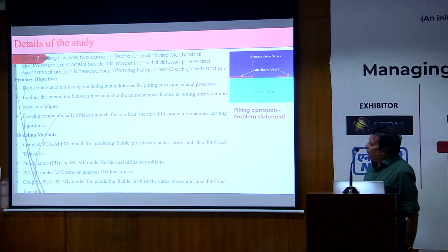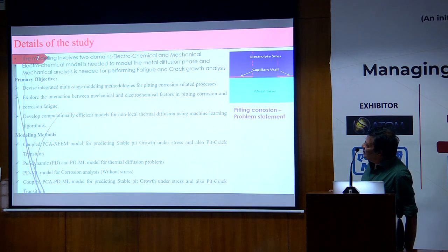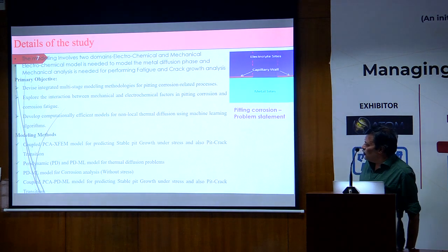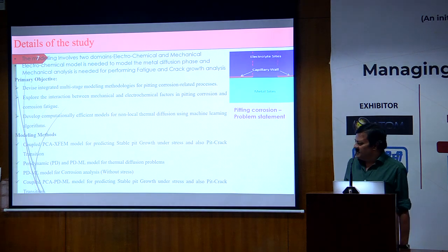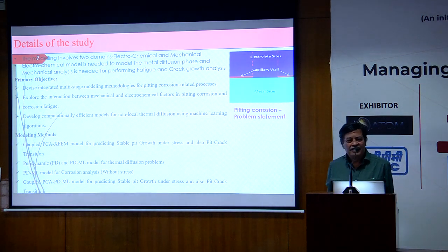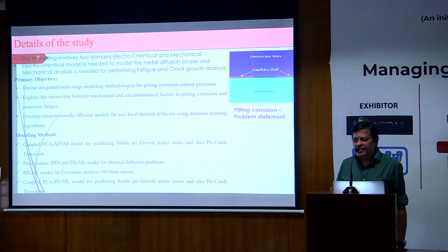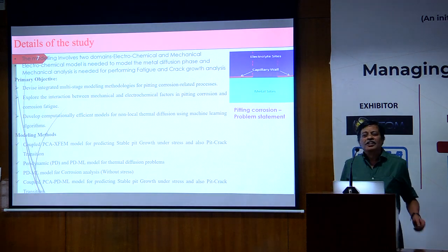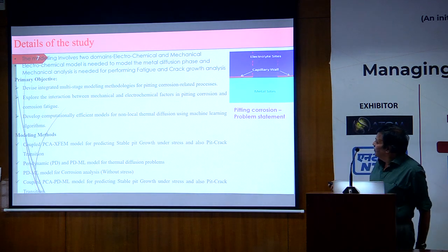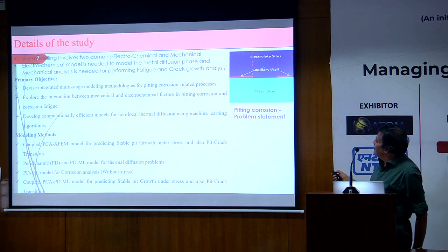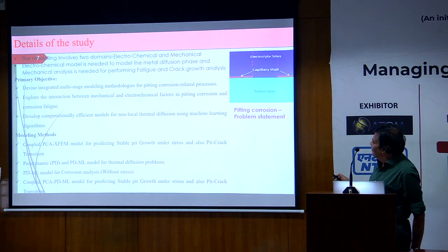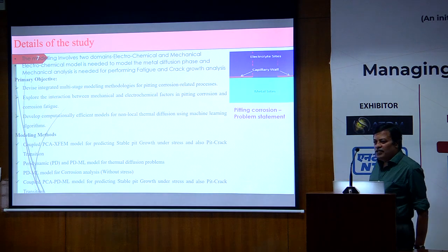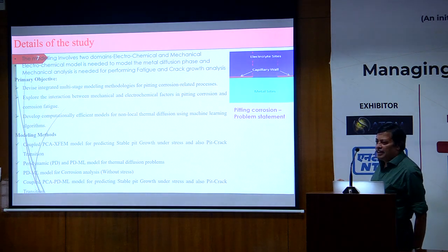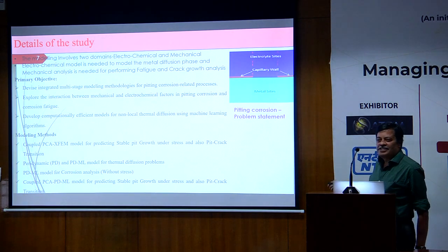So here, what we have done is, basically, we have done a number of different models. Yesterday, Bob talked about the probabilistic cellular automata and FEM model. We extended it to extended FEM because you have two surfaces here. One is the electrolyte side and the metal side. There is an interface, and this interface keeps on changing when the pitting happens.